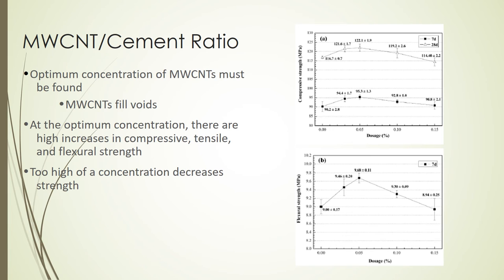The figure shows the relationship between compressive strength and dosage with different carbon nanotube portions added. Due to the nanotubes working by filling voids, as with other components of concrete, there is an optimal concentration with respect to the cement. A higher percentage fills too many voids, and a smaller amount doesn't add enough reinforcement to bridge the cracks. Various studies have come to a similar conclusion as shown on these graphs.